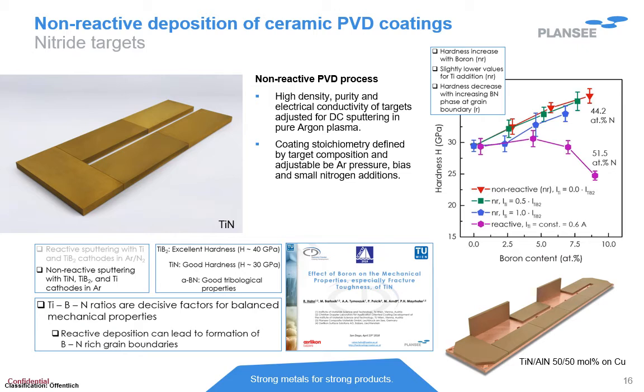The reason is simply related to the increasing amount of boron-nitrogen bonds in the deposited coatings, which is good for low friction coefficient, but not so for hardness. Completely different behavior is shown in case of non-reactive sputtering, where the only source of nitrogen is the titanium nitride target. In this case, the hardness is increasing even to a level of 44 gigapascal for a boron content in the range of 8%. The message of these experiments is that it does matter where the nitrogen is coming from.